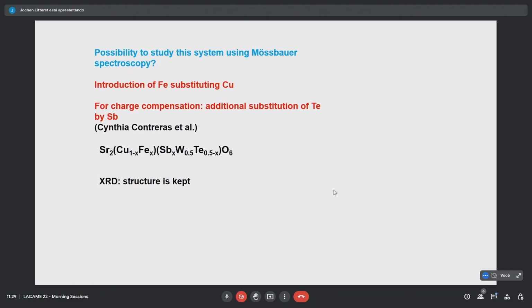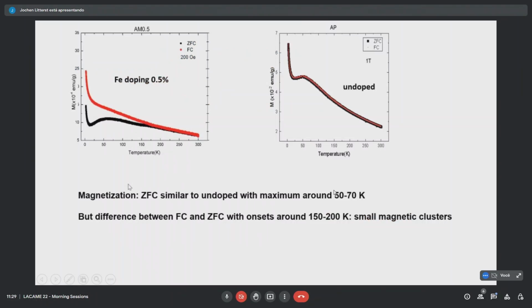So now you will ask, where is Mössbauer spectroscopy to come in the end? There is, in fact, a possibility to introduce iron into this compound. Elisa had proposed that, Cynthia had tried it together with Sami, and to make it short, it works. For sure you cannot introduce iron by itself into copper, so you will get some misfit from charges, so you have to compensate it. The way it's done is that you compensate by introducing some trivalent antimony. This is tellurium here, and in this way you can compensate for the charges. From X-ray, we can see that the structure is kept nicely.